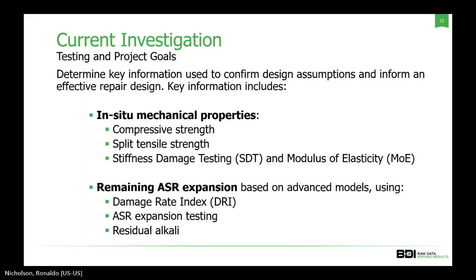Alrighty, so for the current investigation, for testing and project goals, again, we wanted to determine key information to confirm design assumptions and inform an effective repair design that Nick will go on about after this section. Key information included in situ mechanical properties, making sure that the assumptions on these mechanical properties were correct, and if not, course correct for that. This included compressive strength, split tensile strength, stiffness damage testing, and modulus of elasticity. We also wanted to look at the remaining ASR expansion based on advanced models using the damage rate index, ASR expansion testing, and residual alkalis. And these advanced models were performed by Dr. Leandro Sanchez from University of Ottawa.